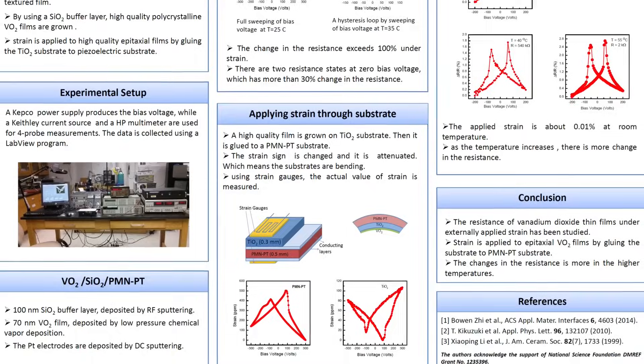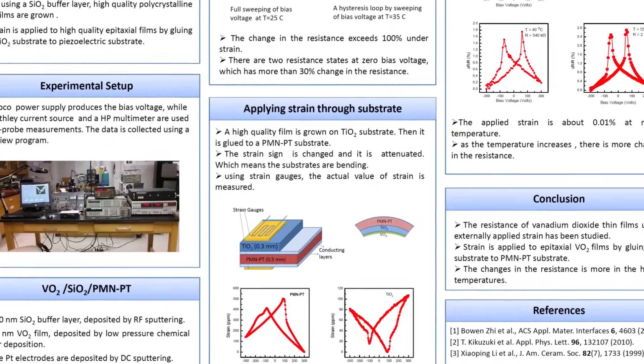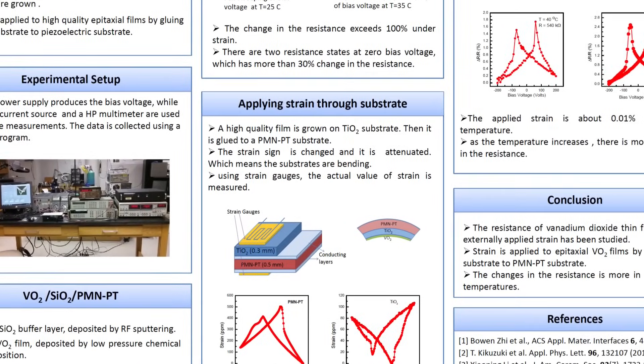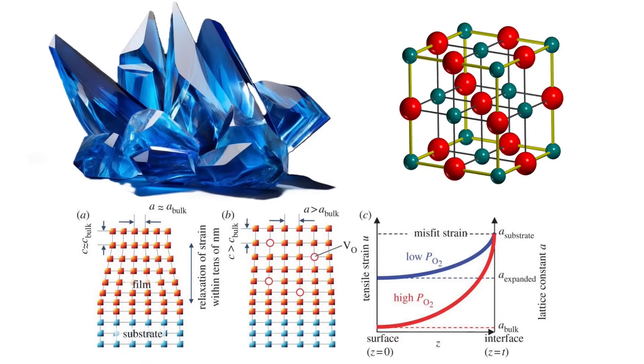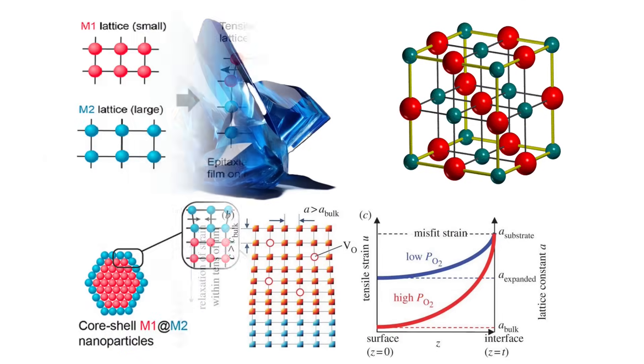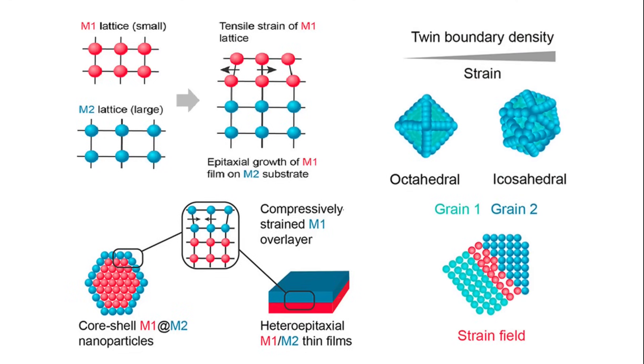If future computers are to use piezoelectricity and work based on the strain effect, we must be able to study strain in a more systematic way. One of the methods I designed aims to fine-tune strain in highly crystalline films. Currently, we can create crystalline films with any desired strain state. We achieve this by using lattice mismatch to grow strained films on different substrates.